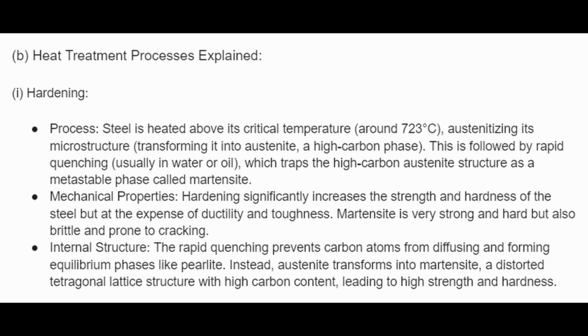Martensite is very strong and hard, but also brittle and prone to cracking. Internal structure: the rapid quenching prevents carbon atoms from diffusing and forming equilibrium phases like pearlite. Instead, austenite transforms into martensite, a distorted tetragonal lattice structure with a high carbon content, leading to high strength and hardness. 2. Tempering. The process.